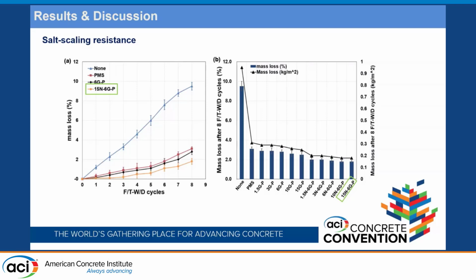Sorry, if I may. This is a rapid freeze-thaw test in the presence of salt. So you're basically accelerating the deterioration in several ways in the laboratory. The water-cement ratio is, I don't remember, probably 0.45 or something. And it was half air entrainment, if I remember correctly. So it wasn't properly dosed with air entrainment, to try to make it deteriorate faster. And the sample is pretty small, so you get a lot of exposure to the salt. And also the freezing rate of this test protocol is pretty fast. In the field, your structure won't go through the freezing cycle that quickly. So all these factors make it deteriorate much faster.